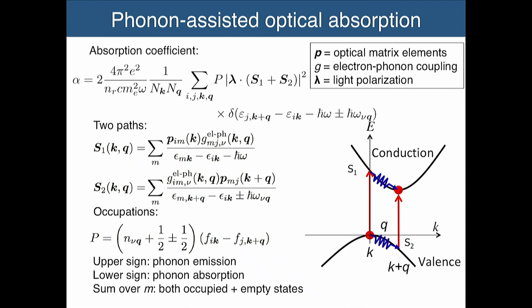And this changed with respect to direct absorption. The other thing that changed is also the matrix element, right? Now, our matrix element is not just a momentum operator. We have to generalize it to account also for electron-phonon coupling. And again, because there are two ways to go from the initial state to the final state, we have to account for two possible paths, labeled S1, where the electron absorbs the photon first and then emits the phonon, and S2, where the electron emits the phonon first and then absorbs the